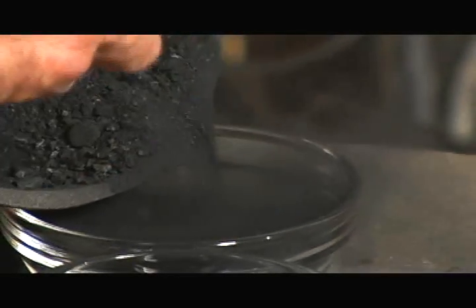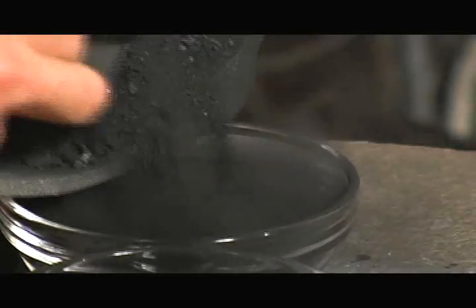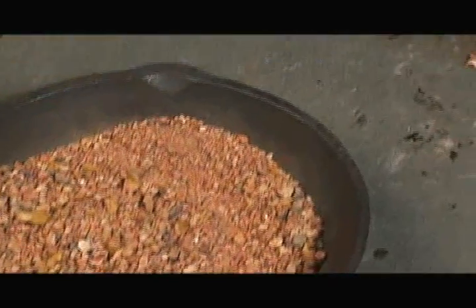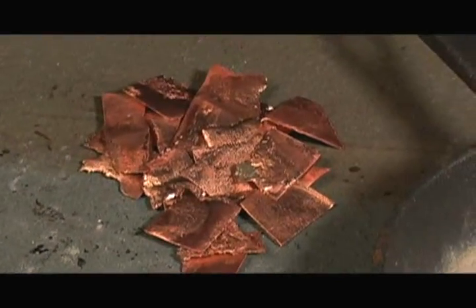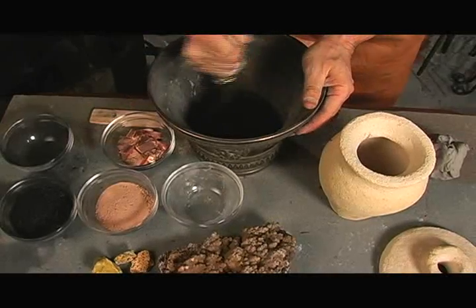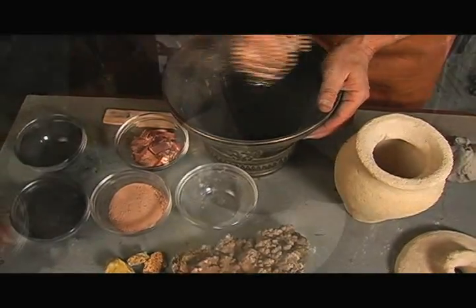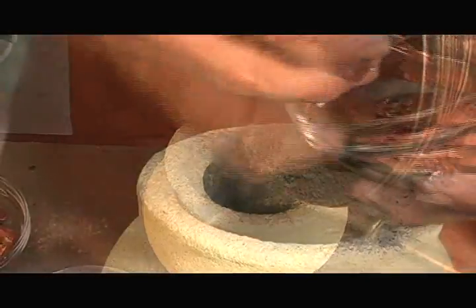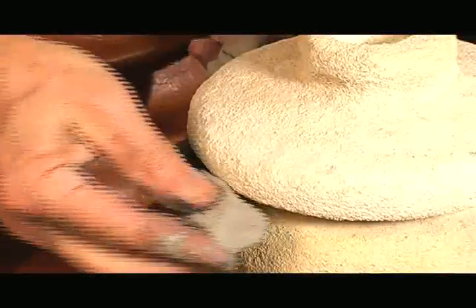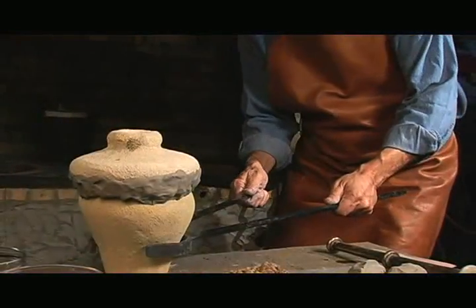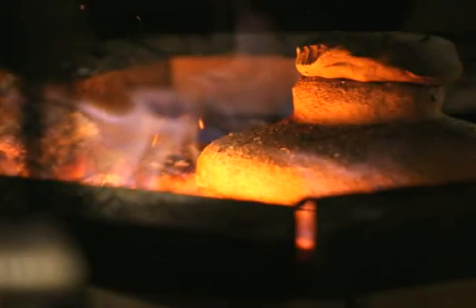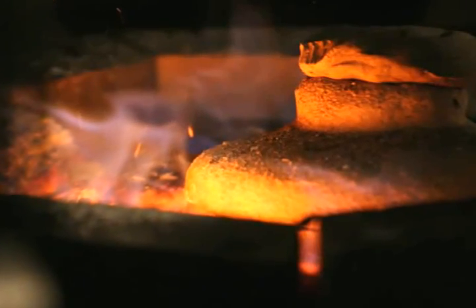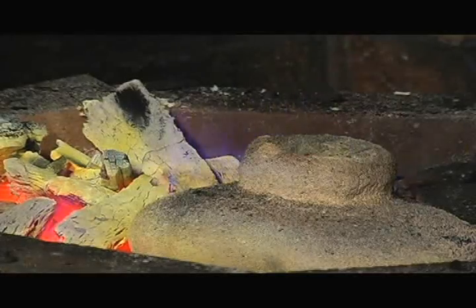In our replication, 2 volumes of charcoal were added to the crucible as a reducing agent, along with 1 volume of roasted hemimorphite and 1 volume of raw copper coupons. Initially, a volume of charcoal was ground with the hemimorphite and placed in the crucible. The copper strips were then placed above the zinc and covered by another volume of charcoal. The lid for the crucible was sealed with clay and the whole placed in the furnace. The zinc and copper were alloyed with one another in a cementation process, which could occur either in open or lidded crucibles. The hole in the crucible lid allowed the color of the charge to be monitored and the contents stirred.